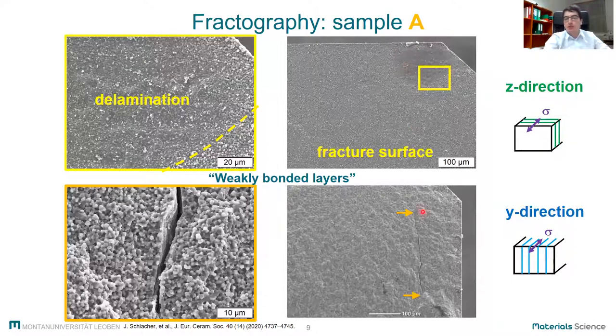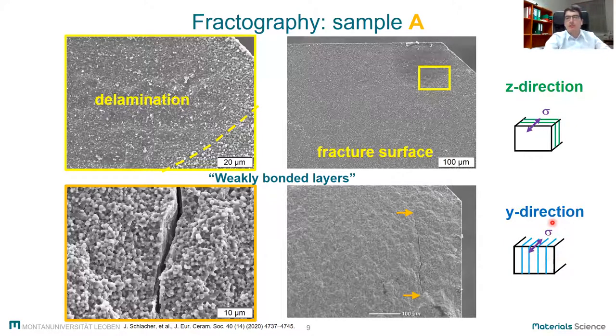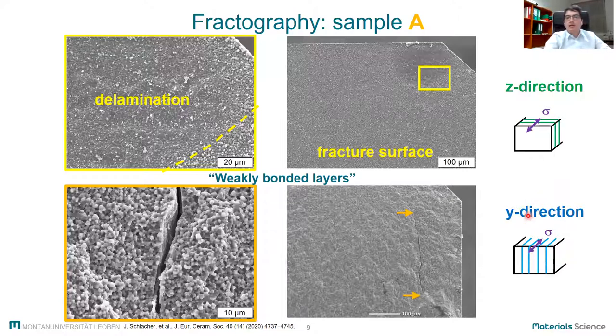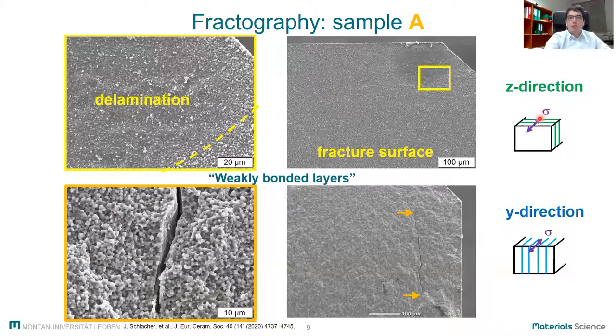Such pronounced delaminations were not found in x and y directions. In those specimens, the load was applied parallel to the layer boundaries and thus possible inhomogeneities were not responsible for failure. This finding indicates that depending on the direction of the applied stress field, whether it is perpendicular or parallel to the layers, the specific defects can limit the strength of a specimen as in z direction, or remain uncritical as in y or x direction.